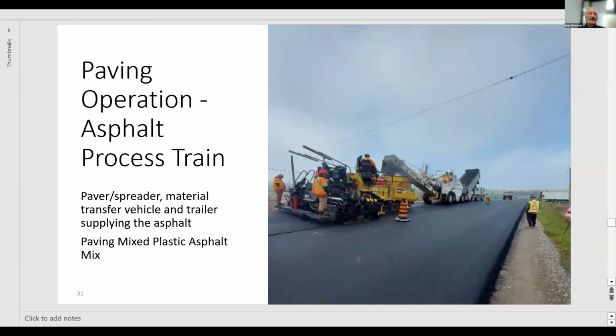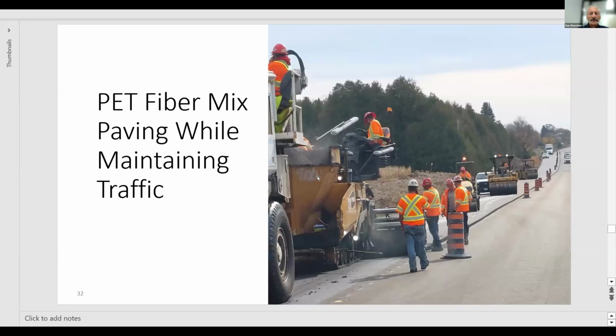Here's a paving operation. The asphalt process train: the paver, spreader, material transfer vehicle, and trailer supplying the asphalt. In this shot they're paving the mixed plastic asphalt, and the mat looked very good. Again, we're very pleased. Here they're paving the PET fiber mix while maintaining traffic. The operation moved along very, very efficiently.